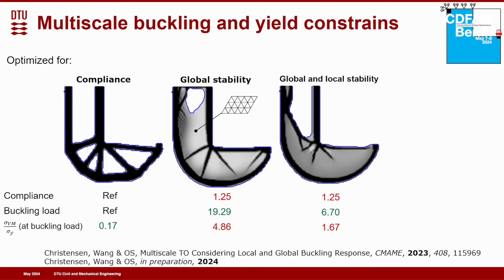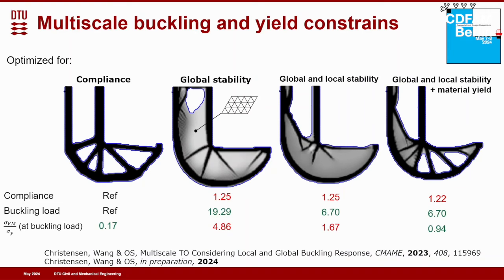So if you also add the yield constraint, we end up with this structure here that is actually a little bit better in compliance, keeps the buckling load, and satisfies the yield stress also. But what we also see here is that latticing disappeared. So this also depends on what material we are building in. So the main message here is it's really difficult to work with latticing, and you have to be critical also. Lattice is not just a nice way to do light weighting. You may also create big accidents by introducing latticing. So keep that in mind. I hope you will think about it.